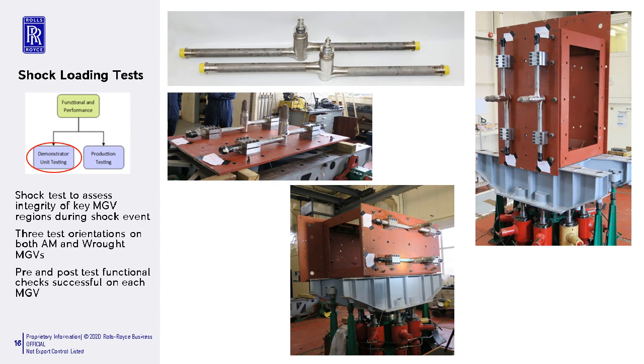So in order to test the integrity of the valve stubs and the valve seats against dynamic loading, we also carried out a series of shock tests on full valve assemblies welded to pipework and mounted on a 2-ton test platform. There were 3 different test orientations, again both with an AM and a wrought valve in order to provide direct comparison. And we applied approximately over 150 G to the arrangement during each test, with the valves water loaded and set in the closed position, as with the majority of the valves in service.